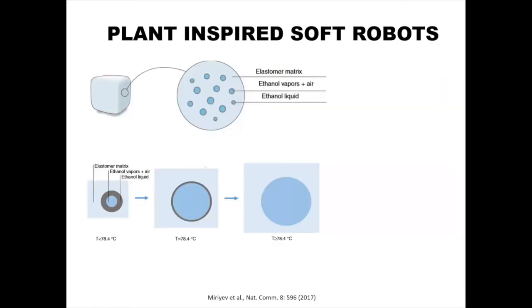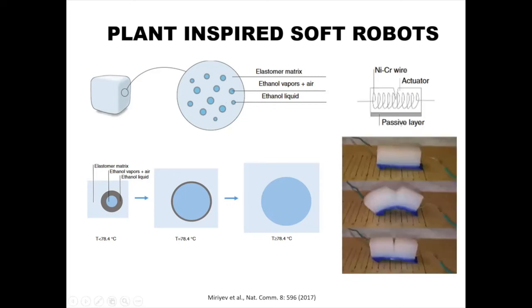One colleague of ours, Aslan Miriyev, took this further. He did not use this reservoir incorporated in an elastomeric bulk material. He just created ethanol drops and mixed them into silicone rubber. So you have this elastomer matrix, you have the ethanol liquid, and you also have a little bit of ethanol vapor and air. By pushing a wire through this material composite and heating it up, the ethanol liquid expands, basically evaporates. And that way you can create this actuating material. So basically it's a composite material.